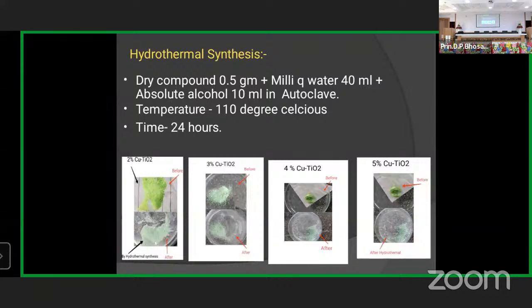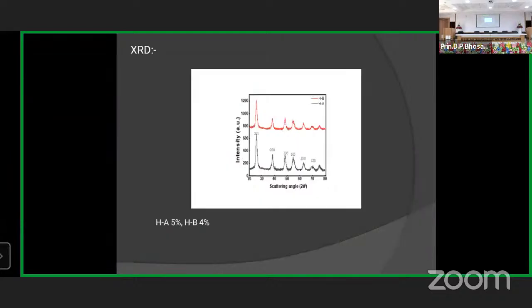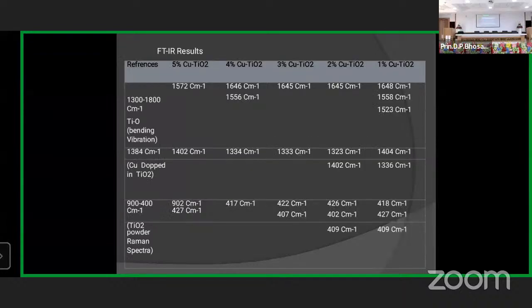So 2%, 3%, 4%, and 5%. All the pictures are here, the data list which I have prepared with this hydrothermal synthesis. Then this is the XRD. XRD indicates that I have got a good anatase phase. Purposely I did the XRD of 4% and 5% because these two catalysts gave us a positive result with the degradation of the bromothymol blue dye.